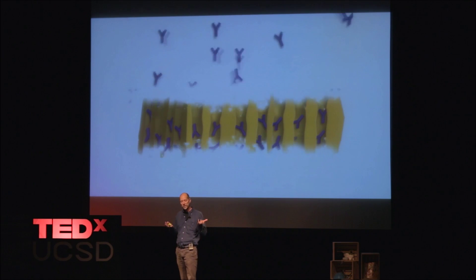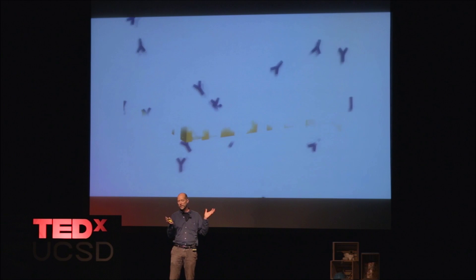Just like a house that gets eaten by termites — before the termites get in, the house is quite stable and doesn't go away, even in strong winds or heavy weather or earthquakes. But once the termites eat holes in that nanostructure, the house degrades and falls apart. That's what we're trying to do in nanomaterials too. By drilling those nanoholes, we cause something that would normally stay — we make windows out of silicon dioxide and it would stay forever in the body — to actually dissolve away in the body in anywhere from four days to eight months. It's amazing what you can do with just drilling some small holes.